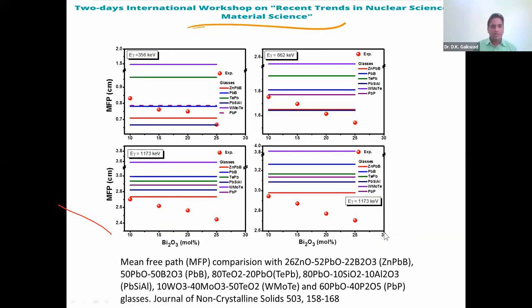Again, this is our study, and we have compared it with other standard glasses at different energies. The red balls are our samples. We have determined the mean free path of the glasses. Our glasses are particularly borate glasses, and they were compared with zinc and lead glasses. Mostly we compared our glasses with lead glasses, as lead has a very high attenuation capacity. Comparing the mean free path of all the glasses, our sample has a low mean free path at 356 keV, exactly equal to the lead silicate aluminum glasses.